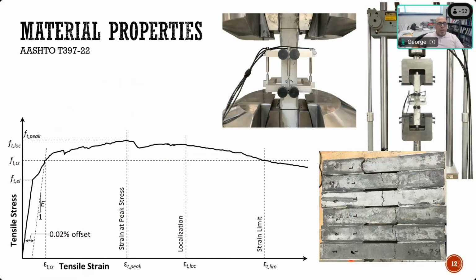So pretty much developing a stress-strain diagram the same as you do with a strand or steel bar. You do that with concrete here because it's fiber reinforced concrete. So you also look at when it first cracks and then how it increases capacity even after the first cracking, and that's what they call strain hardening. For regular concrete, once it cracks, it drops immediately. But for UHPC, because it's fiber reinforced, once it cracks, it still gains some capacity and carries more stress before it starts going down. And that's what's called strain hardening.